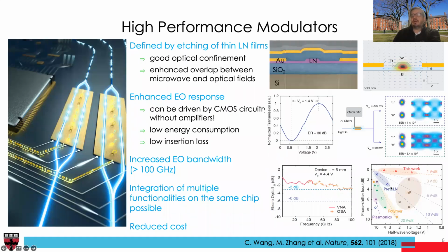And here we compare this type of lithium niobate modulator to, let's say, a silicon photonics modulator in the context of phase shifter loss, basically the loss of the modulator, and the drive voltage. You see that, for example, in materials that are not good electro-optic materials like silicon, you see a trade-off. If you want to have very low drive voltage, you pick up a lot of loss. Meanwhile, in lithium niobate, this trade-off almost doesn't exist. Basically, you can have very low voltage without incurring significant optical loss.